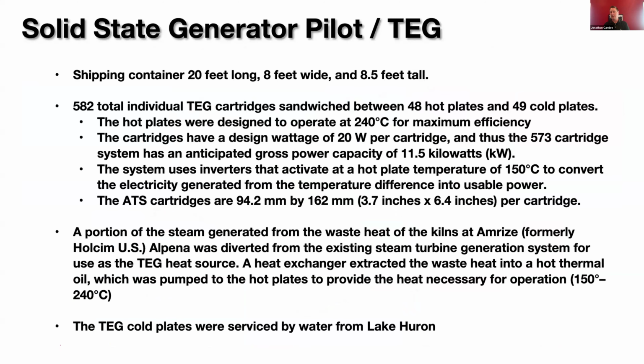So what we have here is a 20-foot long, 8-foot wide, 8.5-foot tall shipping container. We put 582 total cartridges into this unit. Our ideal temperature for maximum efficiency is 240 degrees Celsius. We see generation starting anywhere in the 150 range up, and our ideal temperature for maximum is that 240. That is designed to drive about 20 watts per cartridge at that temperature, and that's our ideal scenario.